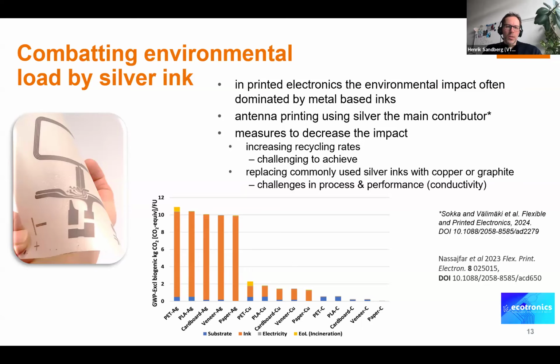But when you change the silver ink into even a copper ink, which is another metal, you see a huge decrease in the CO2 levels, down to 1/5 of the silver version. And then if you can go away from metals altogether, most often you can also see a further reduction. Of course, it's important to keep in mind here that the conductivity of different materials will not be the same. So with copper, you can often reach similar electronic conductivity levels as for silver, but going to carbon or carbon-based conductors will see a decrease. So you have to make some wise choices there.